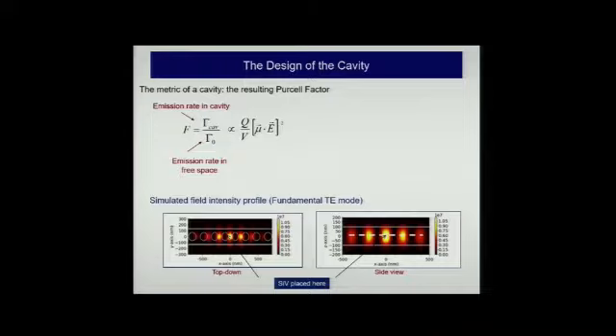It has a relationship to this idea of a very dense electromagnetic field at exactly the right frequency. That is this V, volume. Q is a measure of the low photon loss. So we need to keep the photons in our cavity. We want to keep that standing wave electromagnetic field as dense as possible to exert its effect. And then there's a component that talks about the actual interaction of the emitter, whether the silicon vacancy is here or it's out here. How does that emitter actually interact with the electric field? Is there a strong interaction? Is it the dipolar interaction? Or are they spatially separate so that the cavity doesn't exert very much of an effect?